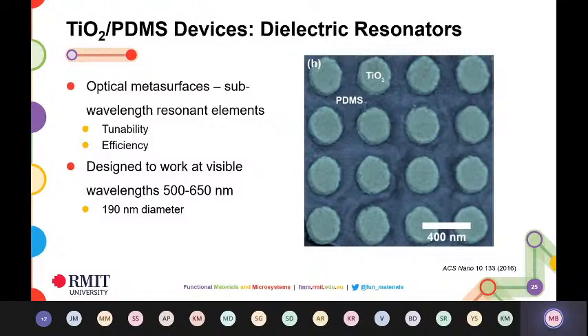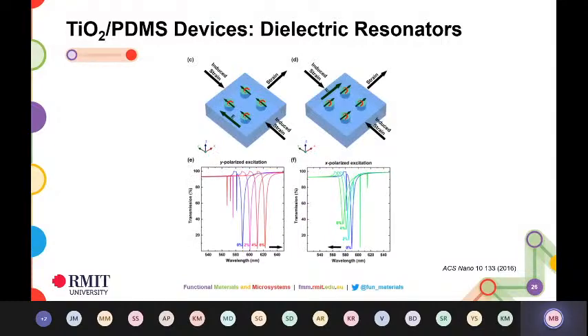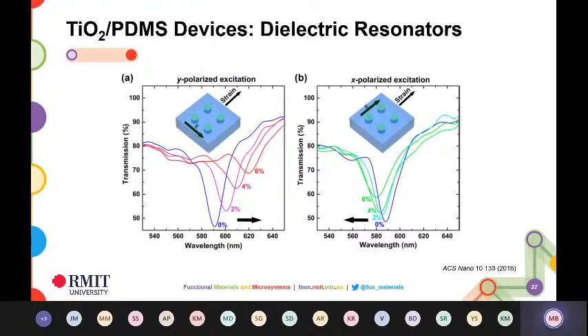So what you essentially have is disks of titanium dioxide sitting within a PDMS platform. These are some of the simulation results they gave us. So what you see over here is you change the polarization of the light, and based on the amount of strain which is being applied on the sample, you are red shifting or green shifting the resonance of the sample. So as you can see over here, it's with y-polarized excitation. You can see the resonance shifting with application of strain. And in this particular case, it's green shifted with the application of strain. These were the simulated results which they sent us. And this was the equivalent experimental results which we obtained back then.